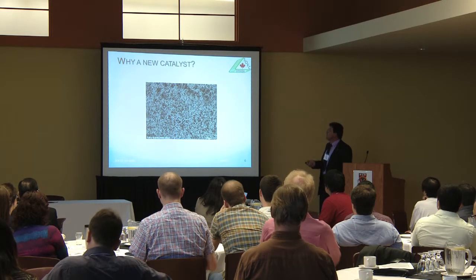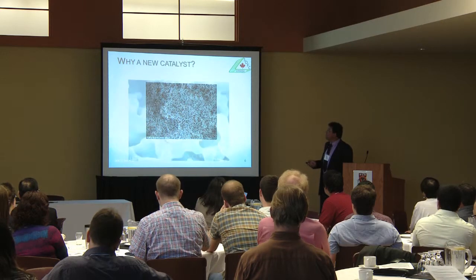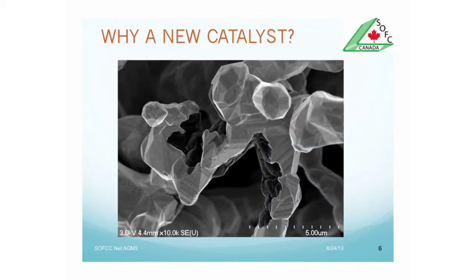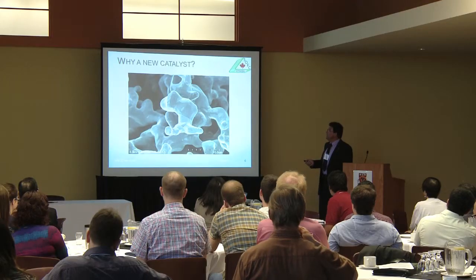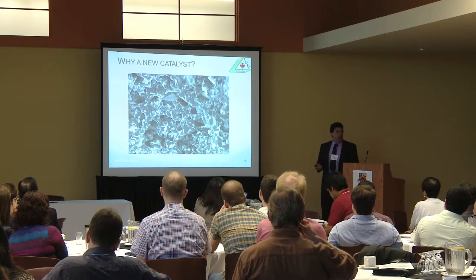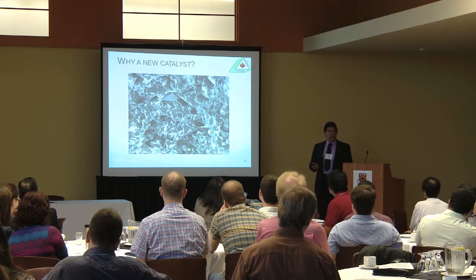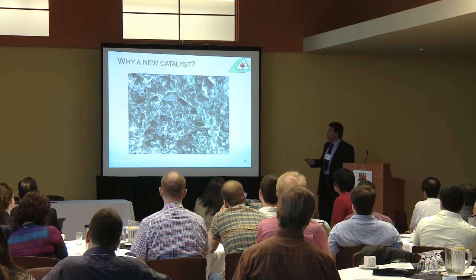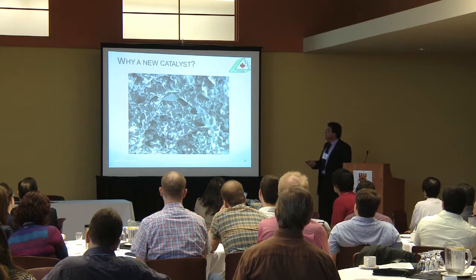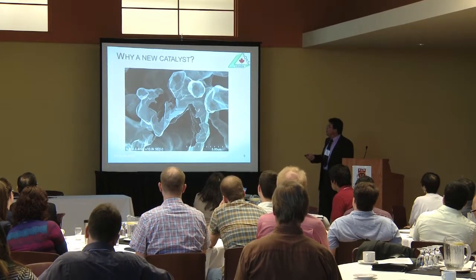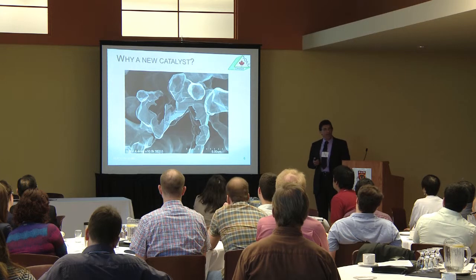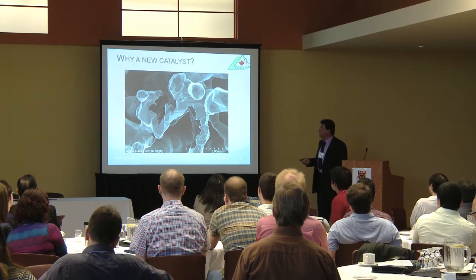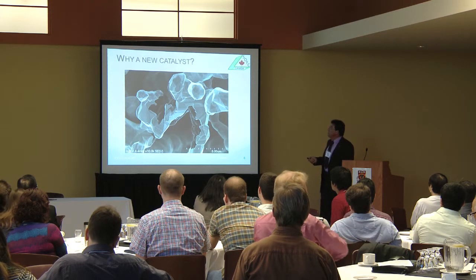For example, we have a catalyst like that which has a big surface. If we see it closely, we see that after use we have some sintering. This sintering means that we have a decrease of the available surface of the catalyst. If we go further, and we do a reaction not with the appropriate catalyst and the appropriate conditions, we have this type of image, which if we go closer, we see this black stuff deposited at the surface of the catalyst and deactivates it: amorphous carbon, or pyrolytic carbon deposited.